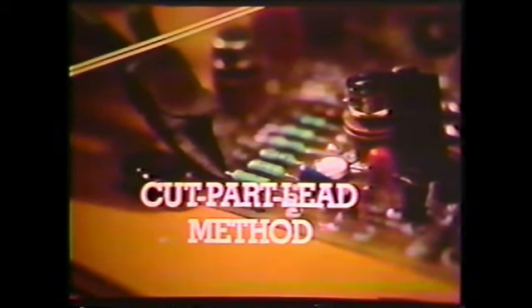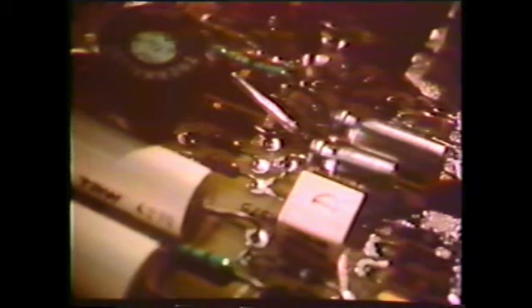The cut part lead method consists of cutting the lead between the body of the part and the solder connection. When the connection is heated, use needle-nose pliers to pull the lead out of the hole. Remove solder from the hole and add the new part. This method of removal is very good for removing machine-inserted parts, such as resistors, because of crimped leads on the back of boards. Resistors are inexpensive and the cost of a new resistor is much less than replacing a circuit board damaged by heat.